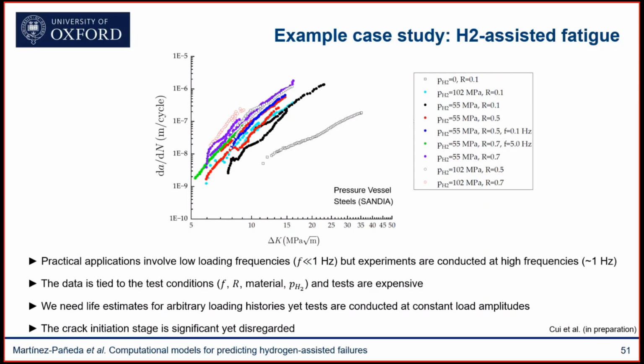And in fact, we know that real applications involve very low loading frequencies, for example, pressure vessels for hydrogen charging. But the experiments need to be conducted at relatively high frequencies because otherwise it's very time consuming. And there's also some challenges related to leaks and so on, when you get high frequencies. So it's a problem because we are on the non-conservative side of things. We are doing fast experiments, and we know that the slow experiments will show more susceptibility, and we know that applications involve slow loading frequencies.